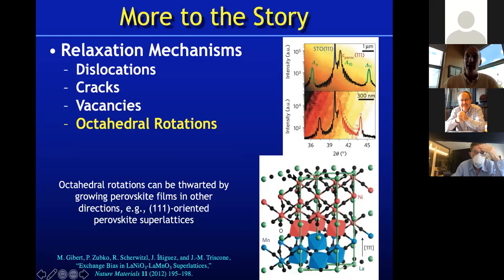111 surfaces can have higher energies, but Professor Triscone and his group were able to find growth conditions that yield very nice smooth surfaces. You can see that from the AFM in the background. You can also see, if you read the X-ray diffraction, there are these beautiful thickness fringes. So it is possible to make very nice superlattices that have smooth surfaces while thwarting octahedral rotations,